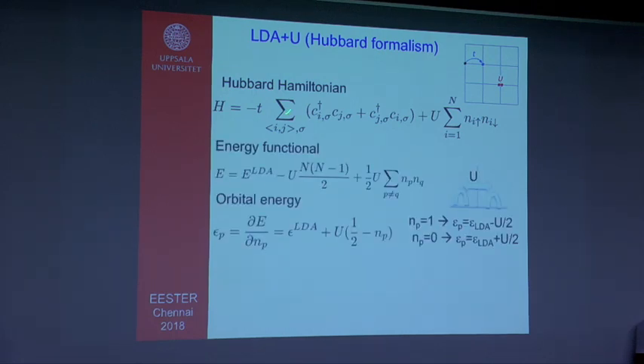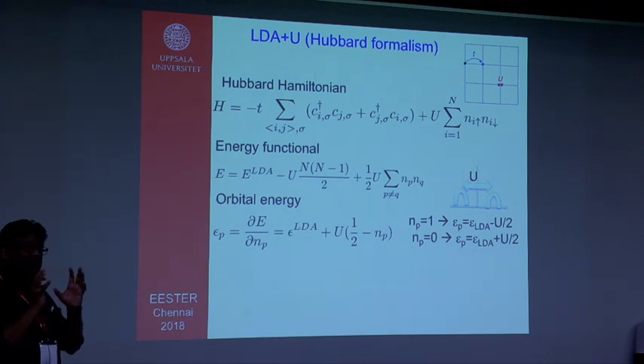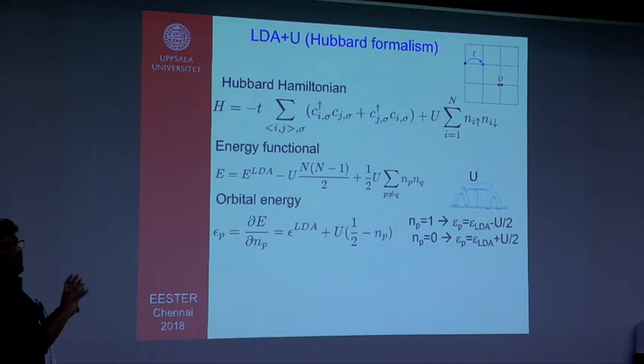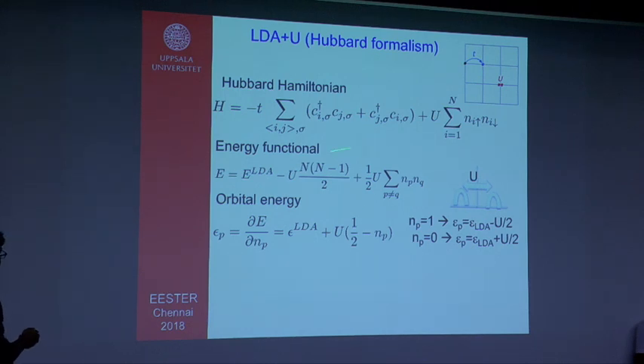formalism. And if you write your energy functional, you can say that this is my LDA energy. I want to correct this LDA energy by adding a strong Coulomb interaction into it. But now I know that I'm doing it a little bit wrong here, because some exchange correlation is already built into my DFT, so I have to take it out. This is the so-called double counting correction. So you add a Coulomb term and you take out the double counting correction from there.